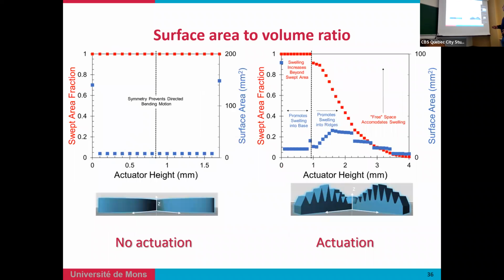How do you do that? Simply, you can see this flower without any anisotropy, very homogeneous. If you swell it in a good solvent, the system will swell in an isotropic way, in 3 dimensions, because you don't have any geometrical anisotropy. But in this case, when you add some peaks, you can have a certain anisotropy, and that will affect the swelling and confer a certain motion when you swell in a very good solvent.